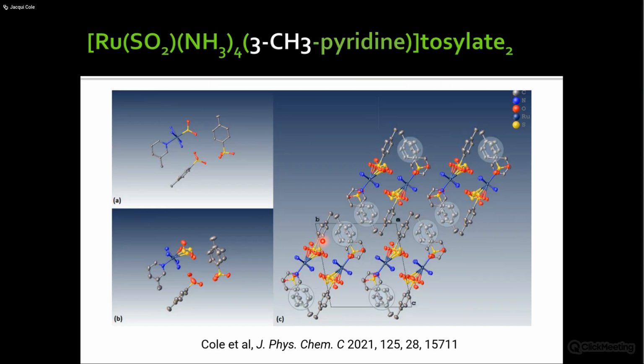Okay, and in terms of what happens when you fire light at these systems, first of all, this is the dark state. Again, this is the crystallographic asymmetry unit, so it's nice and regular, nice and ordered. There's your 3-methyl pyridine, the trans ligand to the sulfur dioxide, which looks very ordered. Then when you fire green light at the crystal and collect the structure again, you see it's now quite disordered, because on top of the dark state you've got this oxygen-bound sulfur dioxide ligand formation. You can see the ADPs of the tosylate group, at least the SO3 part of that anion, are also quite significant. So they're nice and ordered here, now they're not.